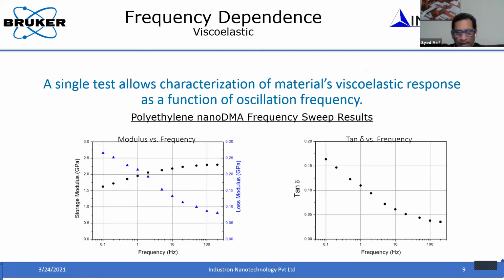If you had to do the equivalent with quasi-static techniques, you would have to load and unload at different rates, and then you have some limitations. Whereas if you do it the way I described, you superimpose a small oscillation and measure the displacement response. These oscillations are very, very small. We call it a small signal approximation. The oscillation amplitudes are so small that the contact size does not change during the oscillation. And then you can also change the frequency of this oscillation.